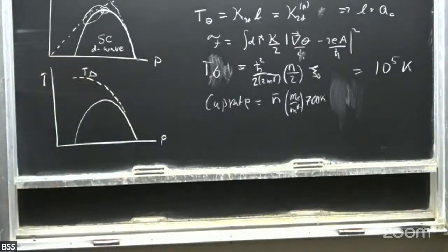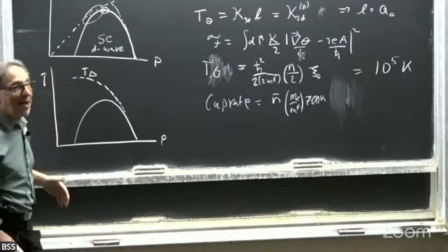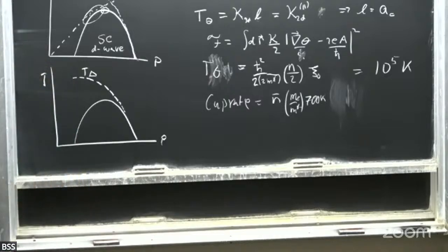And so over here, T theta, first place, has qualitatively different behavior than Tc does. And it can be 3 or 4 times Tc. So, you know, it's not like T theta in lead being 5 orders of magnitude bigger than Tc, but the combination of it being too big and having the wrong qualitative behavior supports the notion that it is not the pairing, but something else that determines Tc.